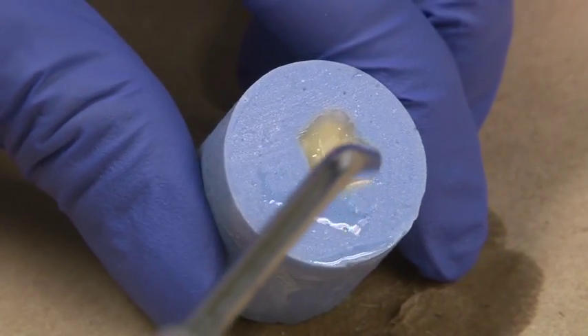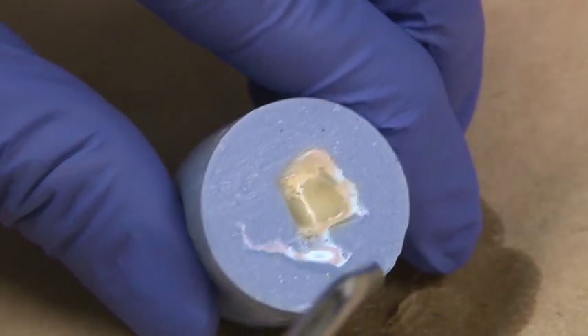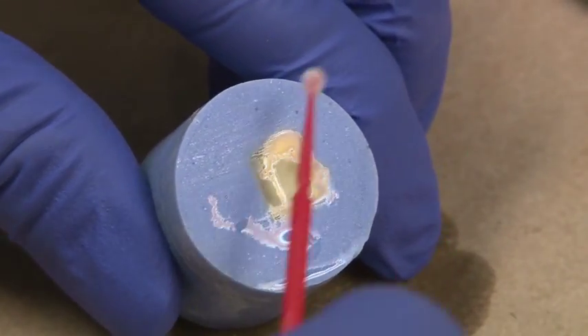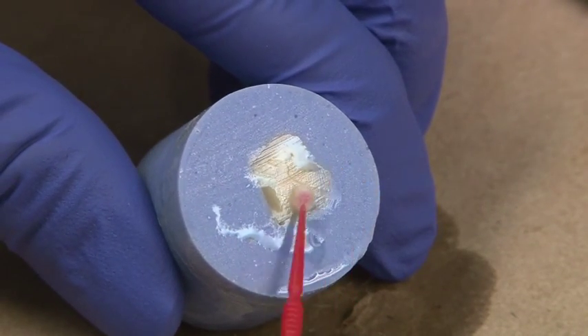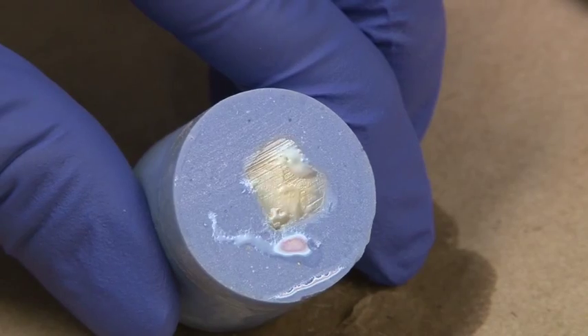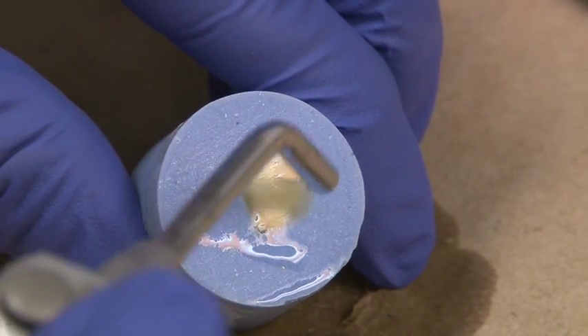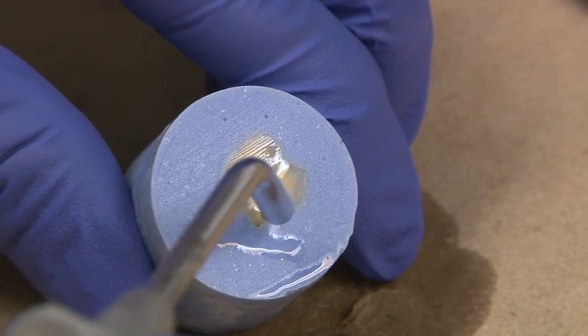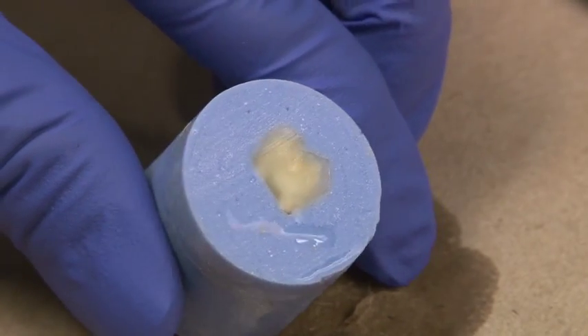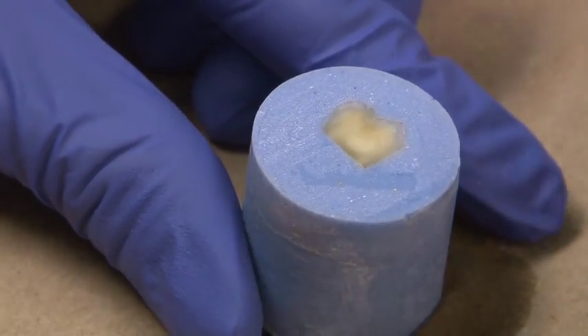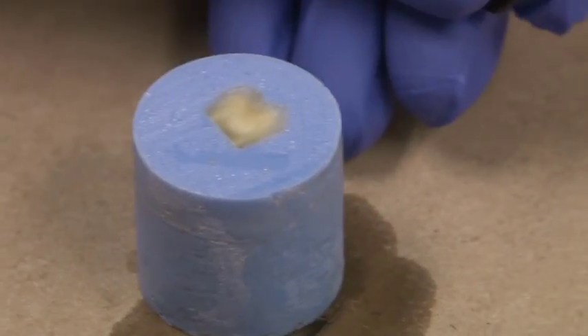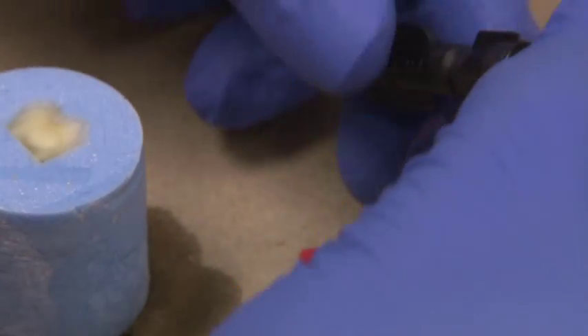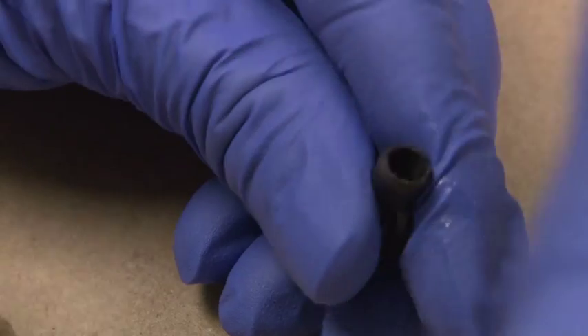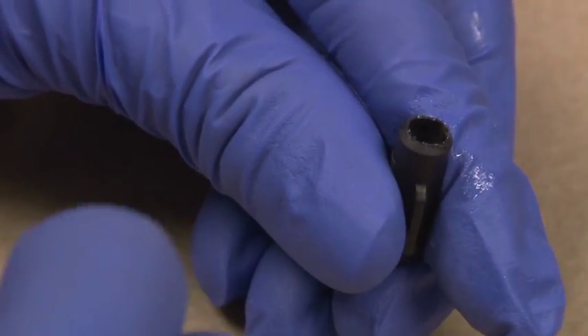if you can see. That is somewhat, that's exactly about the level that you would want of moisture, where the enamel is a little bit drier than the dentin, but the dentin is slightly moist. At this point, I am ready to apply my Optibond Solo, and you need to make sure that this is done quickly right after you've left your dentin slightly moist. Remember, that is sitting there air drying, so if I don't move fast, that's going to dry.